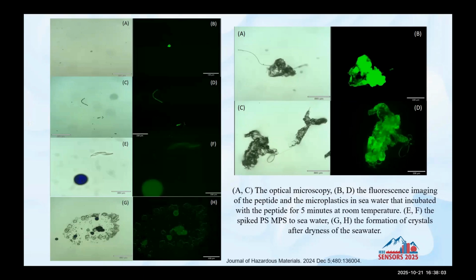We mixed them at the same incubation conditions with the peptide, and we saw in the fluorescence microscopy that there is selective bonding to the plastic, and we couldn't see the rest of the things under the fluorescence microscopy. Also, after drying, these are the dry salts of the salty water of the sea, and you see they are still stable. So the environment of the seawater doesn't impact the interaction between the peptide and the microplastic. It doesn't matter what the shape, the size, or the morphology is. This interaction happens very easily by mixing the peptide with the water sources.